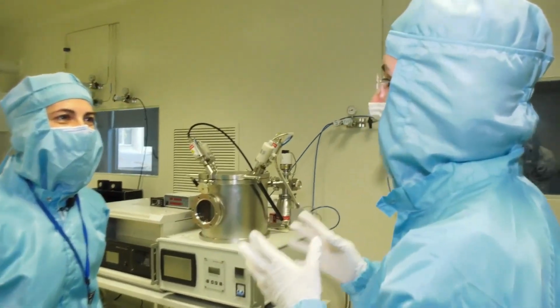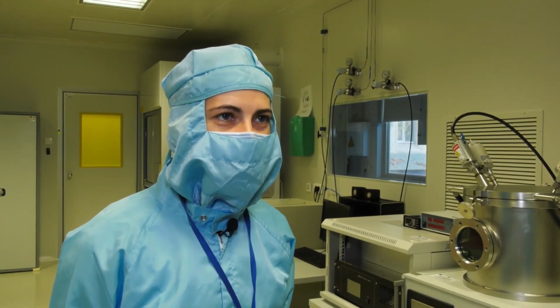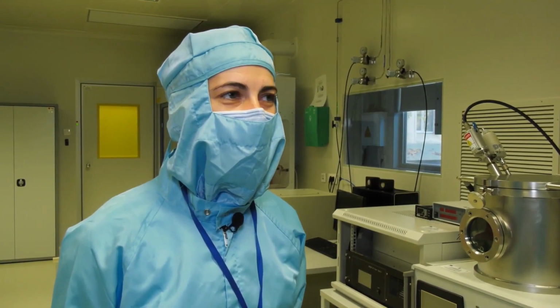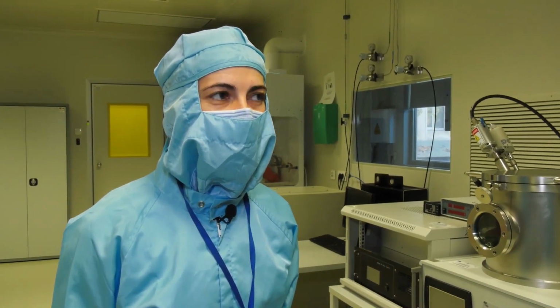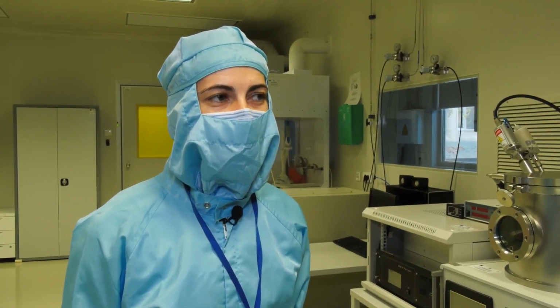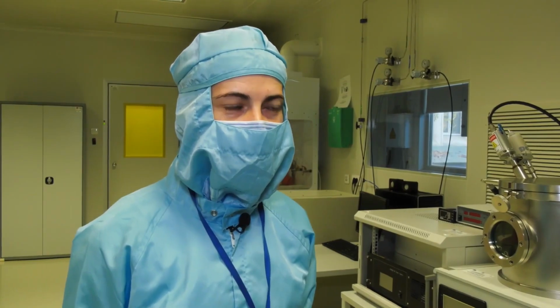Are there any partial results that you would like to share with us? Like I showed you before in the yellow room, we have some lenses made by e-beam lithography that are already published. We have some lenses made by NIL. Also, they are published in a paper. Still, the efficiency for my NIL is quite low. For the EBL metalenses, we are reaching 45, 40. With the NIL metalenses starting from 40, we are reaching just 6% for the moment.